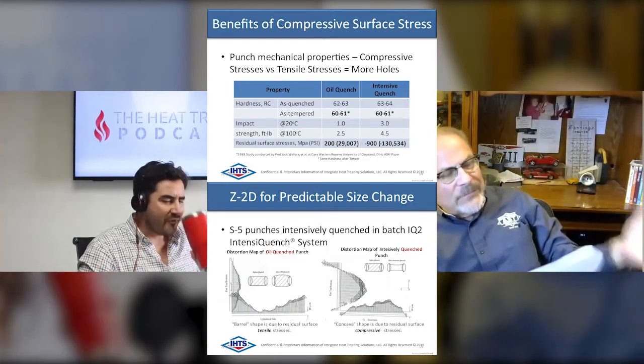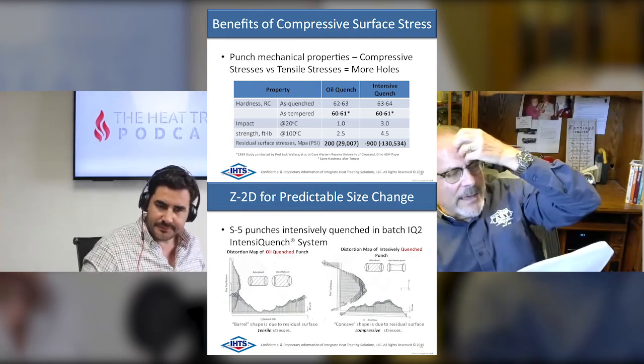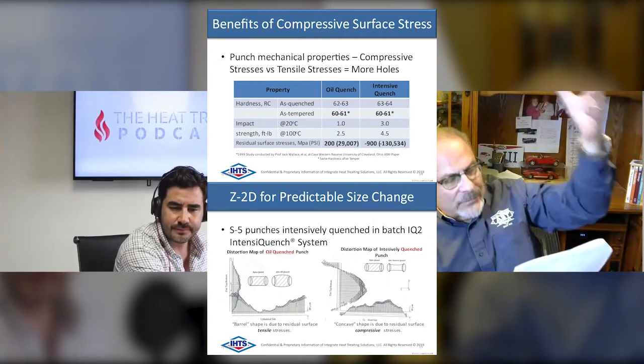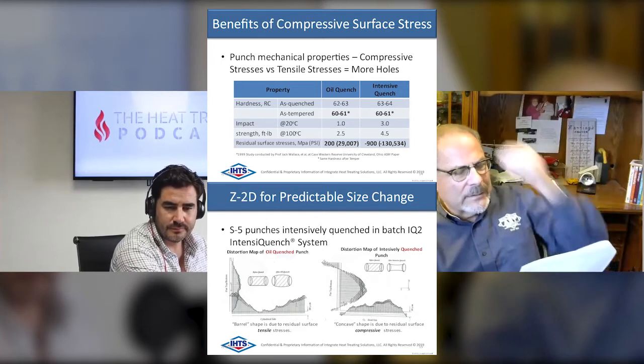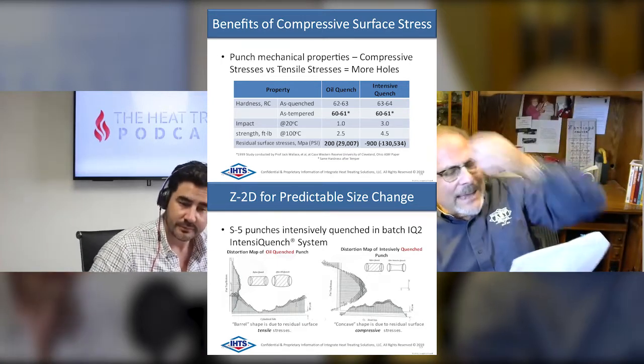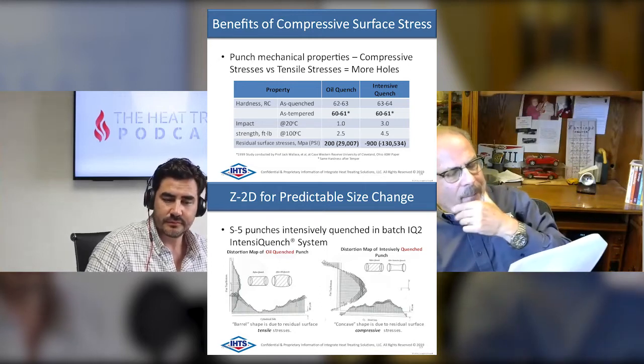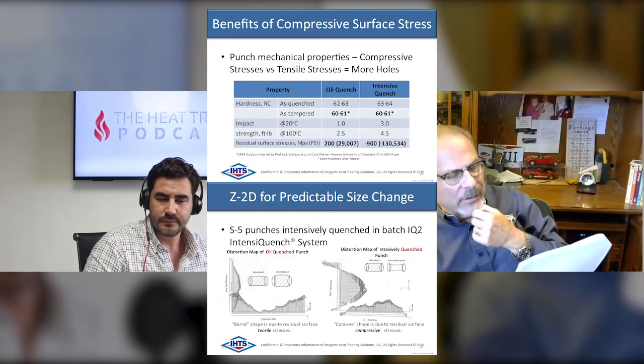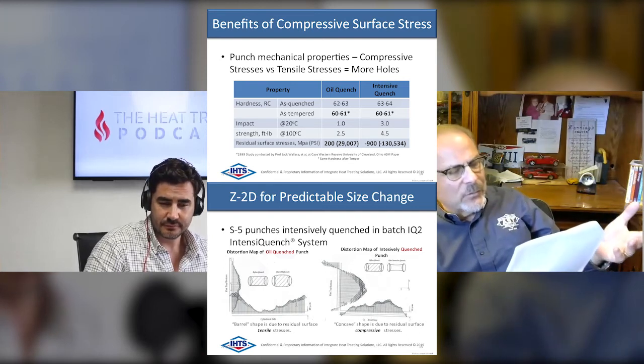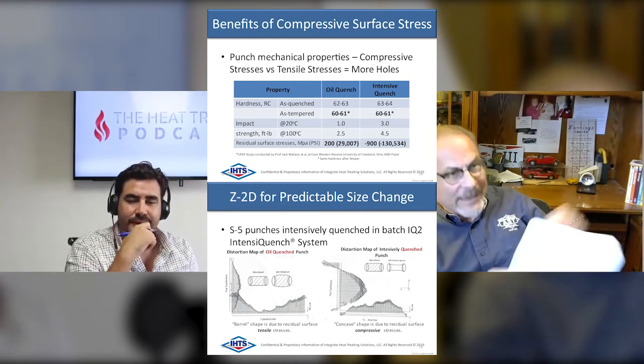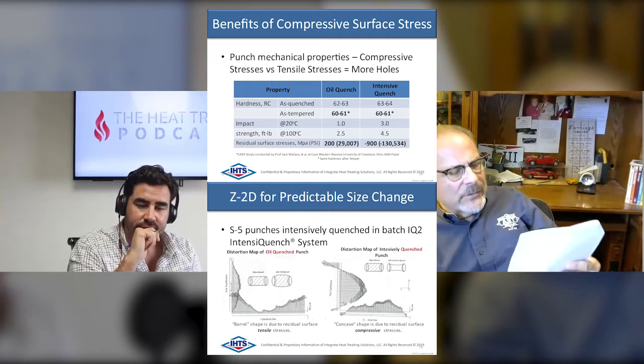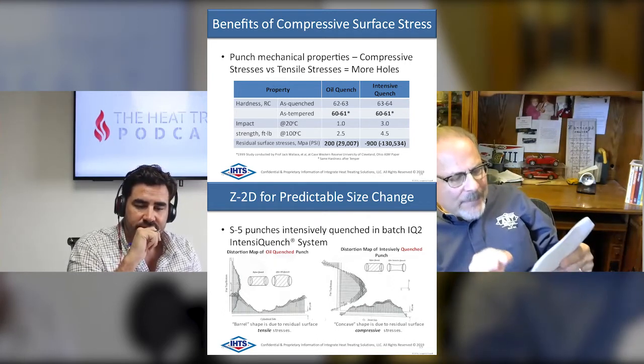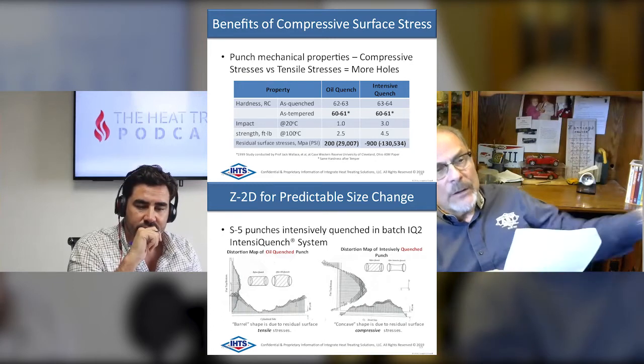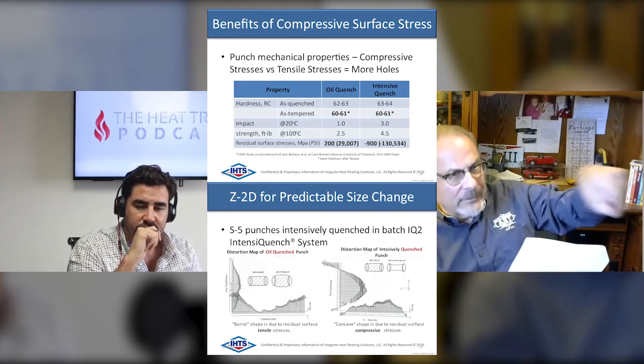But anyway, what we found when we did these punches is that the oil quench punches made out of S5 material were exactly the same hardness, 60 to 61 Rockwell, but they had 200 megapascals of tensile stresses on the cutting edge, which translates to 29,000 pounds per square inch of tensile stress on the surface. And that tensile stress causes that punch to fail after it makes 400 holes, starts chipping around the cutting edge. Whereas the intensively quenched punch had 900 megapascals of compressive stress.